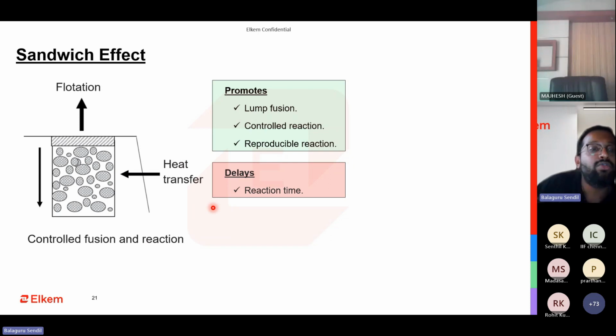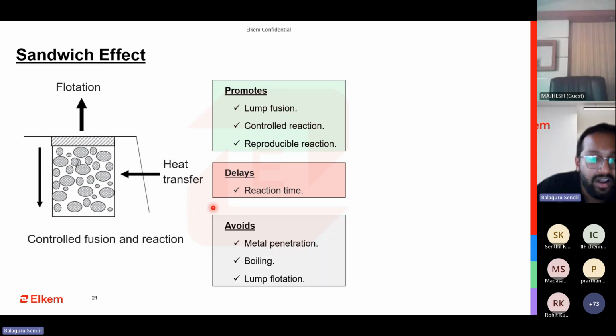At the same time, the other most critical factor we have to look into is the size of FSM that you are using in the sandwich. If you have it loosely packed, you see the smaller pieces going and settling here. But if you're using the bigger sizes, a coarser or narrower size range of 10 to 20, and you're using a cover, you might get away with it. The cover can go and penetrate these gaps. But if the cover addition is on the higher side, or you're not able to get good quality consistent cover, and you're using 10 to 20, what happens?